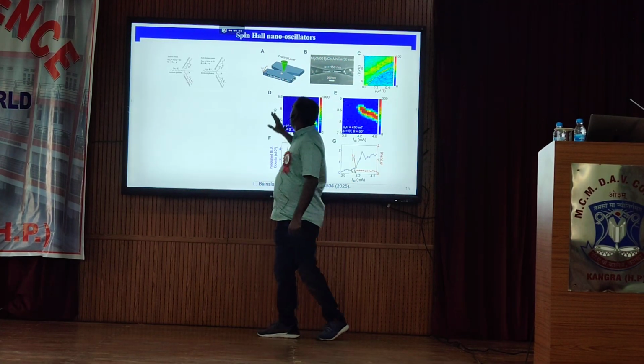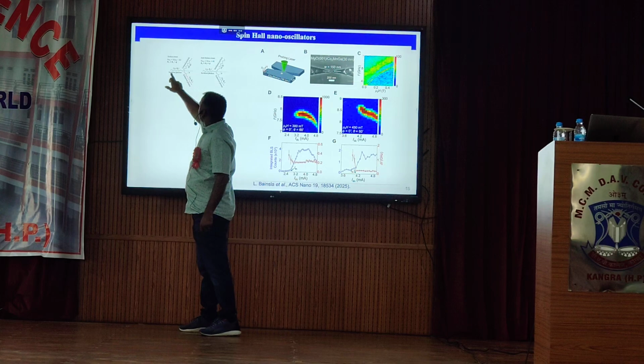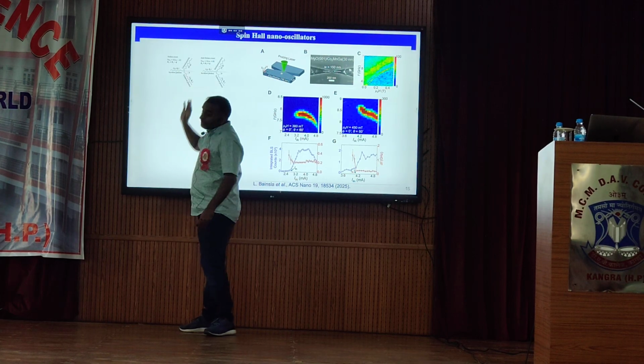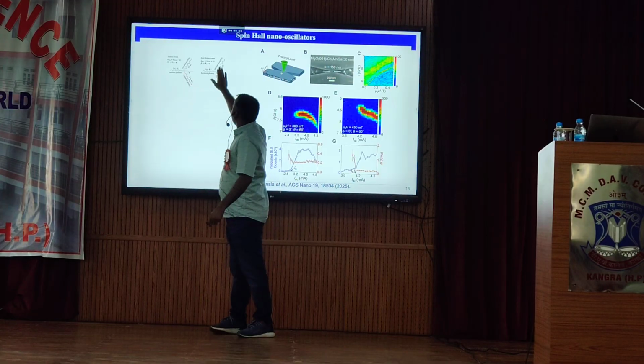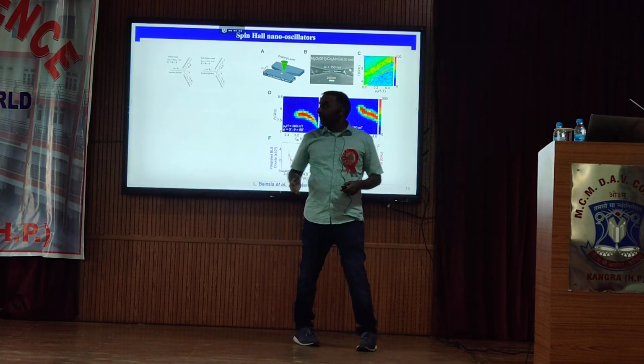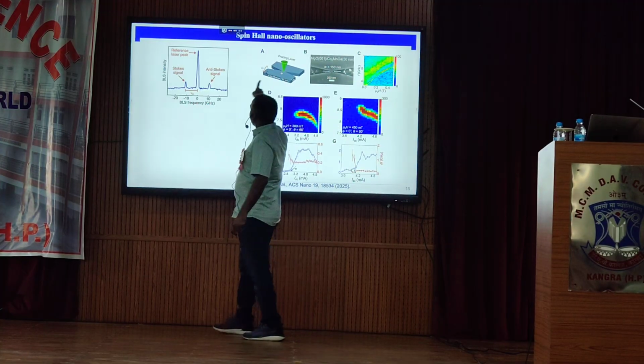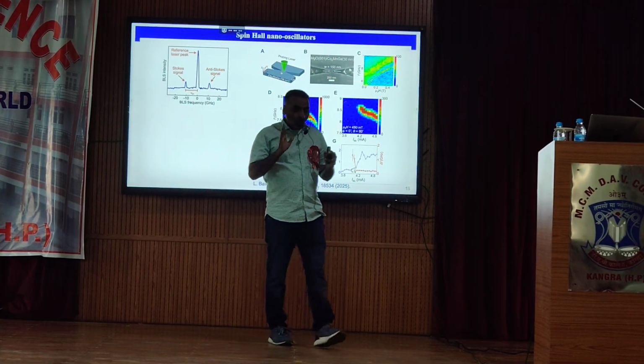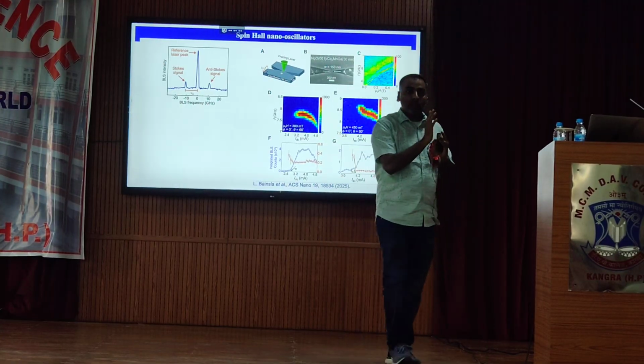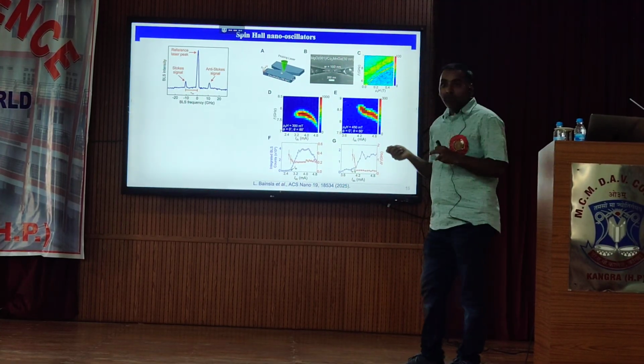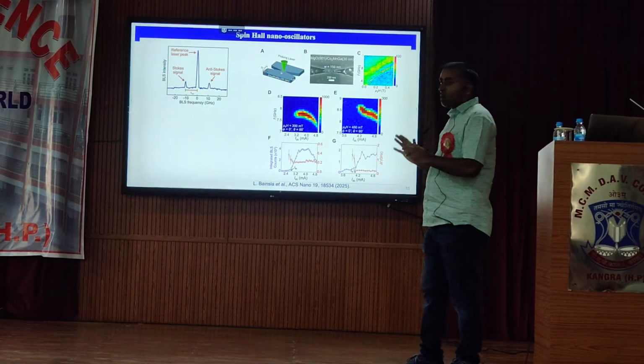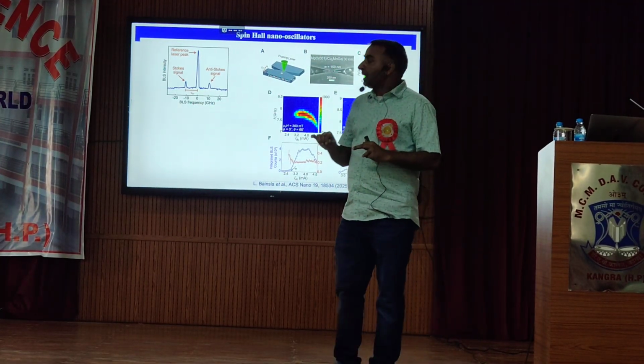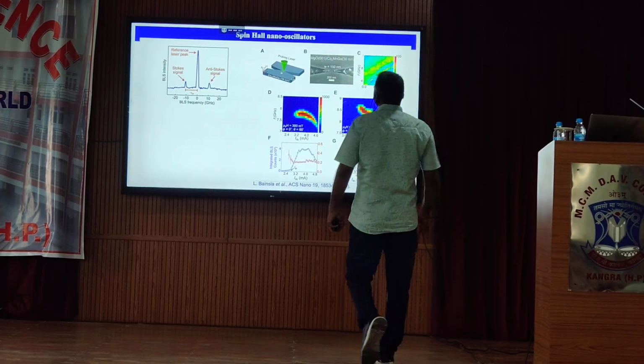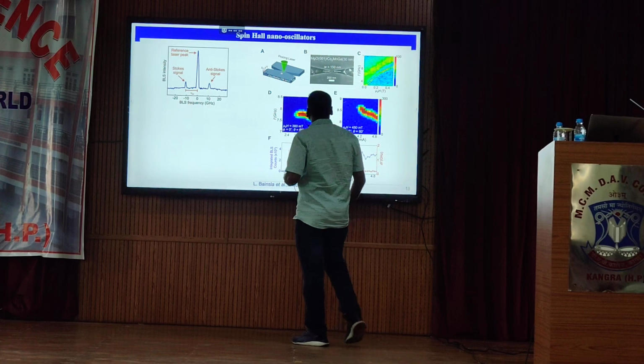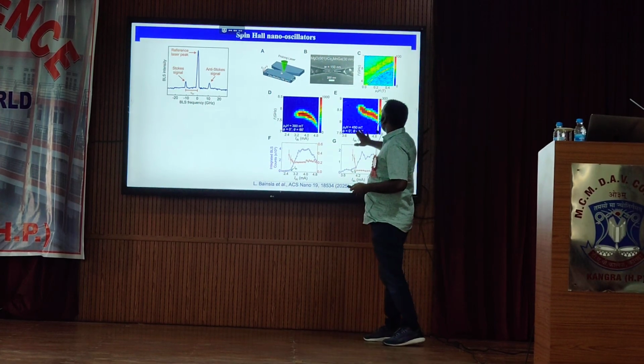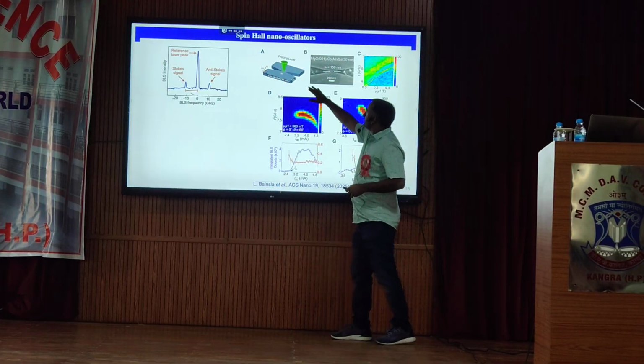So what will happen when we apply this probe laser, the incident photon, to our material? It can either create a particle, which is a Stokes-like event, or eliminate a particle, like an anti-Stokes-like event. So we have a reference laser peak, we know the frequency of that peak, and then we see the shift in the peak of the reference signal. Like if we apply some reference signal in some frequency range, we see with another probe what is the shift in the energy of the applied laser. Depending on that shift, we see either a Stokes-like event or an anti-Stokes-like event. With this kind of measurement, we try to study the magnetization dynamics, because this shows the spin wave.